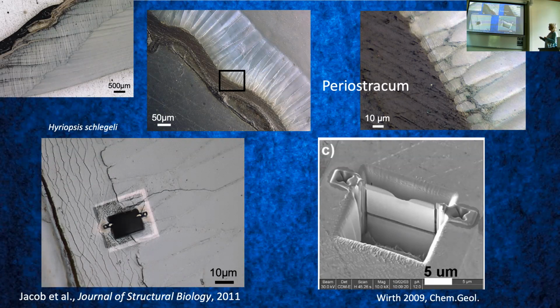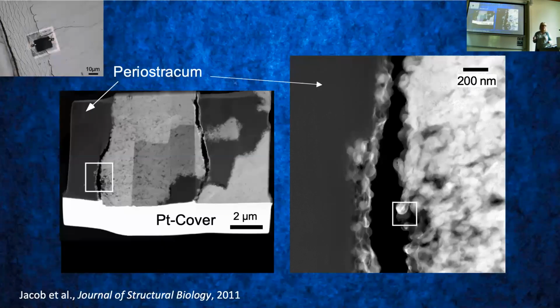The foil often is covered with a platinum strip to protect the area of interest, and that's the platinum strip you will see in the next slide. Then you can take this foil and do all sorts of things. You can do EBSD with it, you can do TEM with it, you can put it in the SEM, you can put it in the SHRIMP if you wanted to. We chose to put it into the transmission electron microscope.